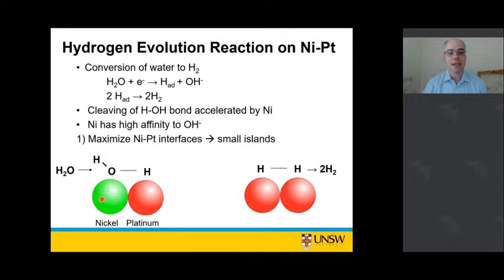the nickel itself has a high affinity for your OH. So the OH part tends to bind to the nickel, and that enables you to break this bond here and get the hydrogen absorbing onto your platinum a lot more easily and a lot more readily. So once we've broken this bond here, we can have two hydrogens on two platinum atoms, then they can join together and form our hydrogen gas.